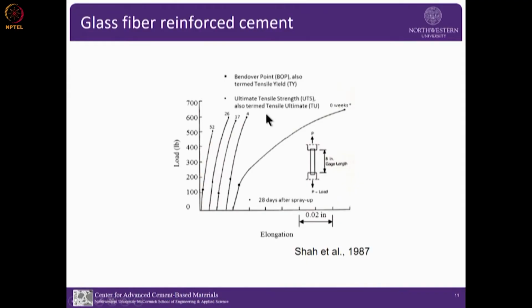and you can see that there is a substantial degradation. So the important point is, even though with single SIC test there was no degradation, in the composite there was substantial degradation. And because, as I said, the glass fibers are made with different filaments, calcium hydroxide goes in and becomes brittle.